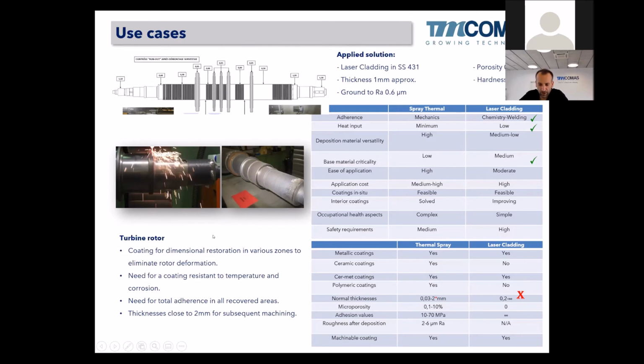So we need a coating for dimensional restoration. We need a material that was resistant to temperature and corrosion. We need total adhesion in all recovered areas. And also in this seal area, we need a coating that could be machined later on to the seal surface profile needed. So the best option here is laser cladding. So we ended up applying laser stainless steel 431 again, in some areas 1 millimeter, in some areas 2 millimeters, and then we machined everything, we ground everything, we ground also the coupling areas here, the conical one with some taper.